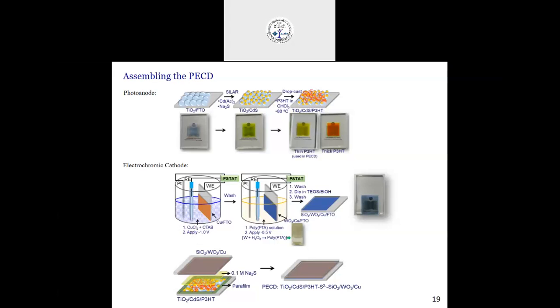Yes. So, what is the size of the CdS quantum dots formed onto the layer? Particularly using the SILAR method, the size is sometimes around 10 to 20 nanometer, because SILAR sometimes tends to grow on top of the other one. So I cannot say it is absolutely below 10 as it should be for quantum dots. It's around 10 to 20. But if you ask about the TiO2 and CdS layer thickness, then the entire thickness is in the range of 10 micrometer.